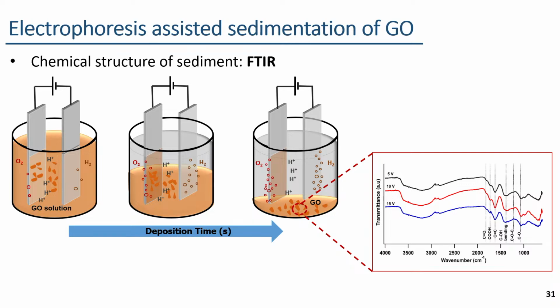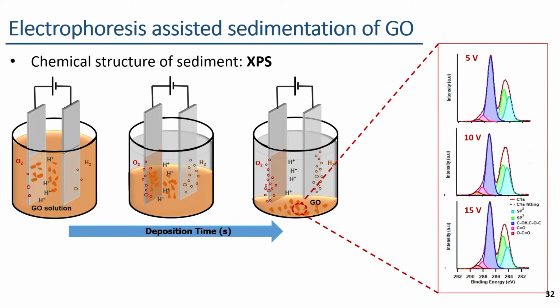Here I have shown the FTIR spectra of these sediments separated under different voltages, and in these spectra we can see the same IR peaks corresponding to the oxygen functionalities of graphene oxide. So, this confirms the presence of graphene oxide even in the sediment. When it comes to the carbon 1s XPS spectra of these sediments separated under the different voltages, here we can see a similar amount of total basal plane functionalities among these three samples.